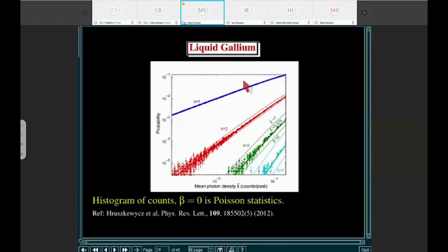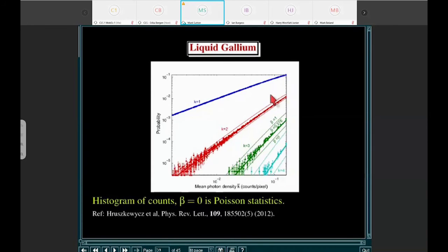And so actually what we do is we measure very low count rates. Here we looked at count rates from 10 to the minus 3 counts per pixel to 10 to the minus 1 counts per pixel. But because of the coherence, the statistics over many, many pixels deviates from Poisson statistics. And by how far it deviates from Poisson statistics, we can measure how coherent the beam is. Here, you can see in the red curve, or the green curve in particular, that the number of pixels that have two photons deviates from the upper curve, which is what Poisson statistics gives, and it's in between that and the bottom curve, which is what a fully coherent beam gives. And so here, we've shown that we can see a static speckle pattern from liquid gallium, which means we can resolve the time constants at the liquid gallium structure peak with our X-ray beam, and so we can in principle do XPCS with this two-pulse technique.